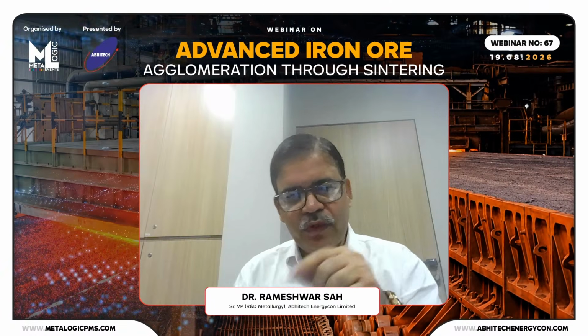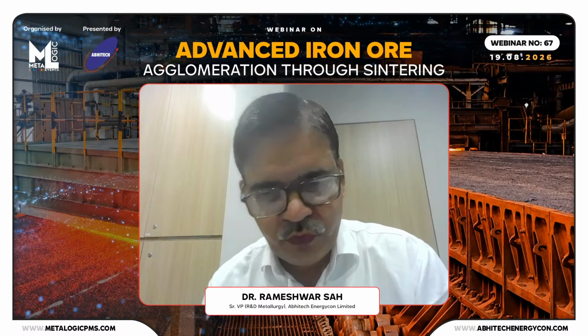So to handle this goethite ore microstructure during this process, it requires more heat, so more coke breeze will be required. If you know it is goethite ore, and if you have the phase analysis of how much goethite is in the overall sinter blend, then we take charge of the fuel consumption. Normally goethite ore requires a little more of the solid fuel, so that the process does not become energy deficient, where we could not make the proper melt, the partial fusion of the material, which would obstruct the proper bonding during the sintering process.